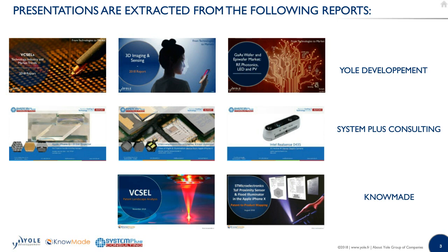Yeah, sure. So yield is really one of the major problems to enter the VCSEL business for 3D sensing. Making VCSEL for datacom is totally different than making VCSEL for 3D sensing. As I mentioned in my presentation, when you move to 3D sensing, there is a transition to 6-inch manufacturing. And today, the yields are really low at epitaxy and at chip manufacturing level.